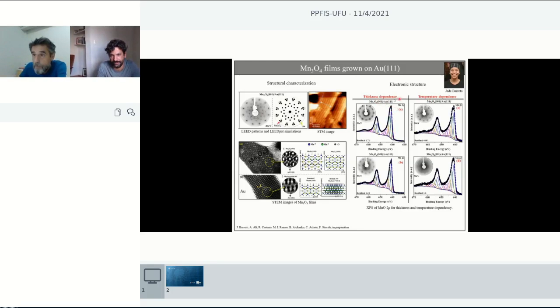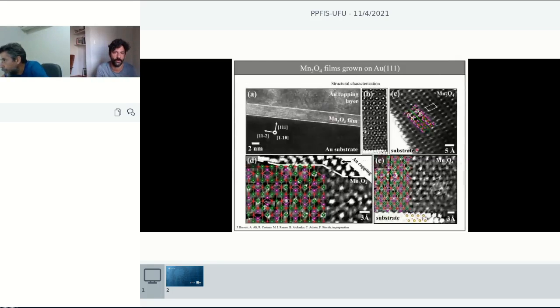All you see here is a thickness dependence and temperature dependence. You see Mn3O4 in the same plane of growth direction, but you see that the peak shape changes for each one slightly, and these changes are telling us the small changes that we actually have in the amount of low coordinated sites in this kind of film. So this is very helpful, and this is also something that we can correlate with higher resolution images.